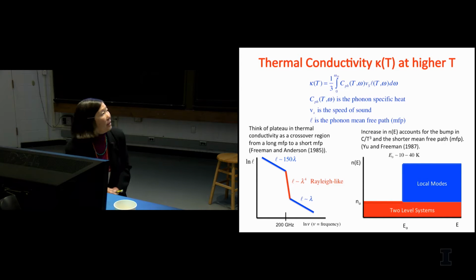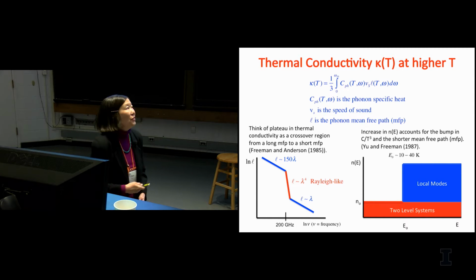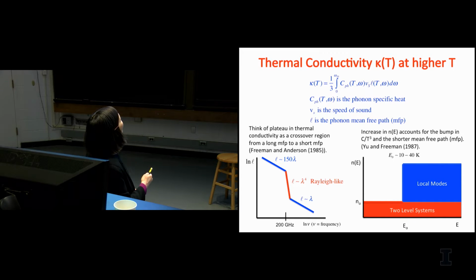Well, if you write the thermal conductivity a little more precisely, it is an integral over the specific heat, the speed of sound, and the mean free path. The mean free path is a function of temperature and frequency. And you can use that as a fitting parameter to fit the thermal conductivity. Freeman and Anderson did this. If you plot log of the mean free path versus log of the frequency, at low frequencies you get a very long mean free path. The mean free path is about 150 times the thermal wavelength, and that's where you get the T-squared thermal conductivity.